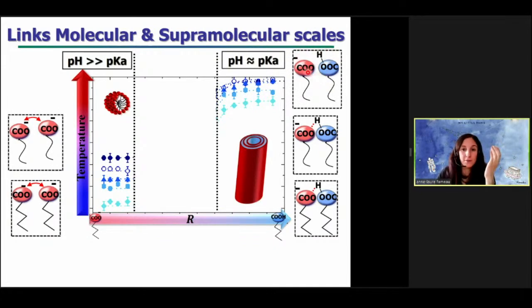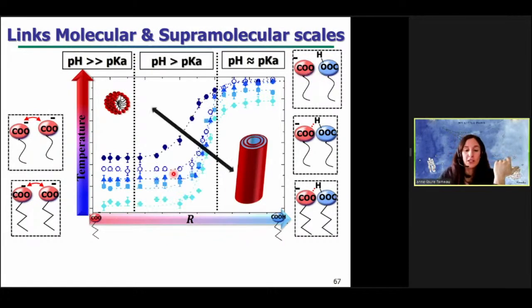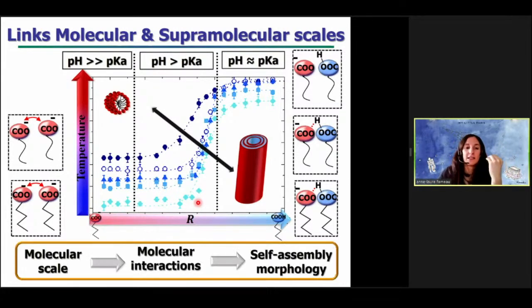So you have a surface melting that changes the packing parameter, and you have the formation of spherical micelles at high temperature. And here the second regime is just an intermediate regime, because when you increase the molar ratio, you progressively increase the quantity of protonated molecules inside your system and the quantity of hydrogen bonds inside your system. So it's really the change at the molecular scale, from the alkyl chain state, from the gel state to the fluid state, or at the head group level, that can explain the different molecular interactions, this different self-assembly morphology, and the wide temperature range for the tubes to micelles transition.